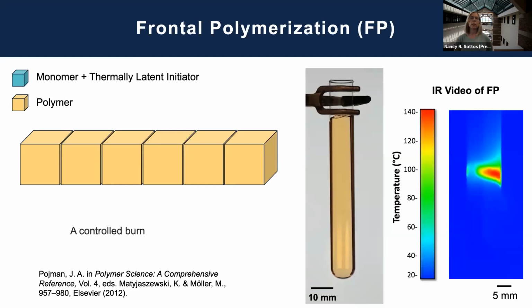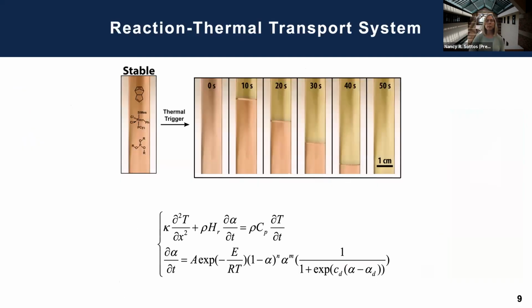If we look at this in an IR video, and this is an IR of not the same test tube, it's actually a little more zoomed too. And again, it started just after the point where it's been initiated with a soldering iron, so just a small heat trigger. And this will give you, again, a feel for how the heat is generated due to the reaction and then diffuses and propagates down the tube. So you can see red here is a hotter temperature. It starts to react. The heat starts moving forward, and the reaction front, again, smoothly moves down through the test tube, curing the monomer. Okay, and it's just about finished. All right. So if I take some snapshots of that and just freeze them on this slide, you can see again that you start out with this stable monomer, and you can see the smooth propagation of the front.